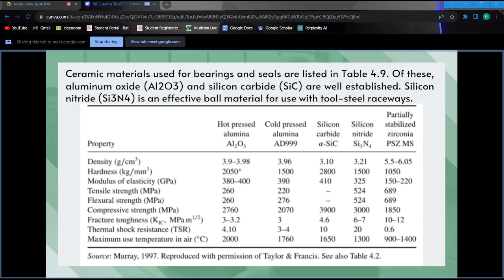We have silicon nitride naman po or yung tool steel, we have a density of 3.21 grams per cubic centimeter, hardness at 1,500 kilogram per square millimeter, and modulus elasticity of 325 gigapascals, tensile strength of 524 megapascal, flexural strength is 524 megapascal, compressive strength is 3,000 megapascals, fracture toughness is 6 to 7 megapascal, thermal shock resistance 20, and maximum use temperature in air is 1,300 degrees Celsius. Next po.